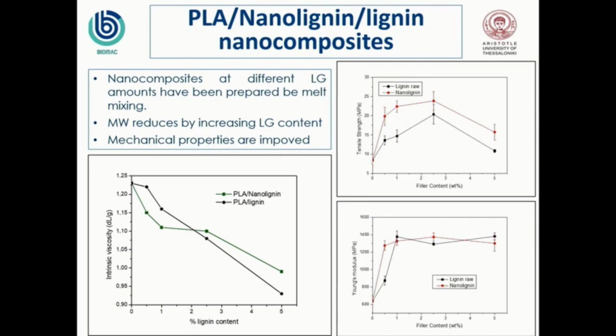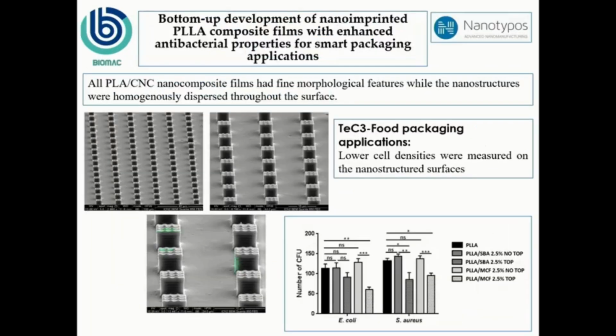The gain here is that there was a substantial increase in tensile strength. You can see there, starting from about 6 megapascal, after adding 2.5 weight percentage of nanolignin we succeeded to go to about 25, about 5 times higher. And also, the Young modulus increased again.